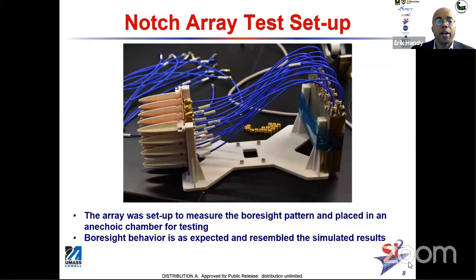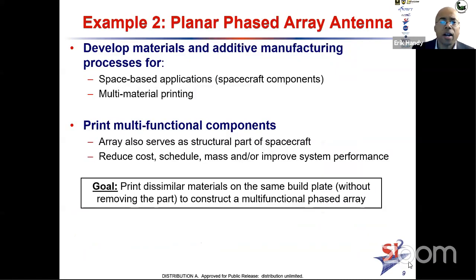And just showing here, this is that same 4x4 Vivaldi array, wired up and ready for testing. We put it in an anechoic chamber. And when we look at the boresight pattern, we see performance corresponding to what we expect from simulations. So this is one of our first 3D printed antenna programs, very gratifying that we achieved the success that we did. Onto a second example, switching gears a little bit now.